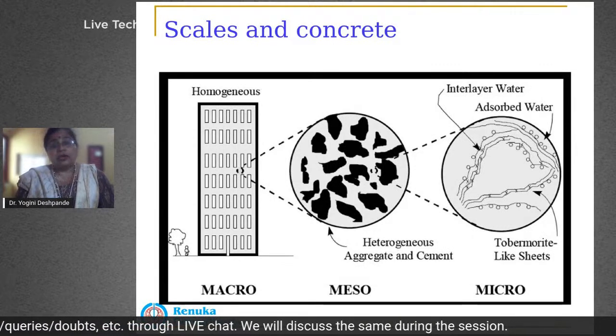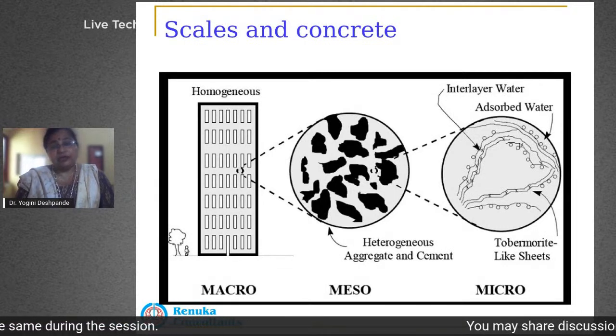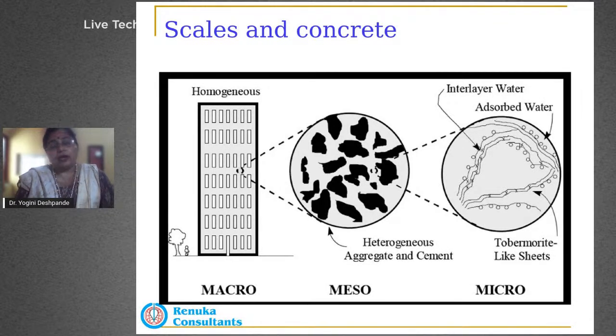The other way around, if we have a fire in a building, or any fire in a concrete structure, the structural failure happens because there is a large change in the microstructure of the concrete, and there are chemical changes that happen within the concrete during a high temperature fire, which cause structural failure, which may or may not be evident after the fire is curbed. So there's this aspect where we have to, as civil engineers, be conscious about what is happening at different scales and how each is affecting the failure aspect on a long-term basis.